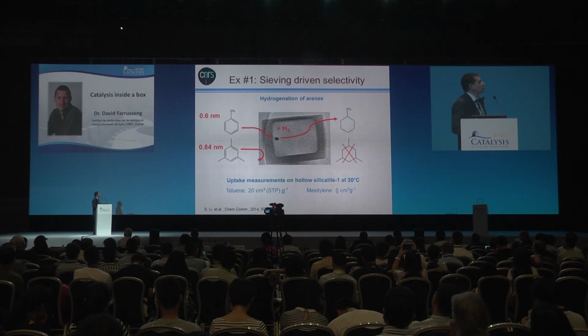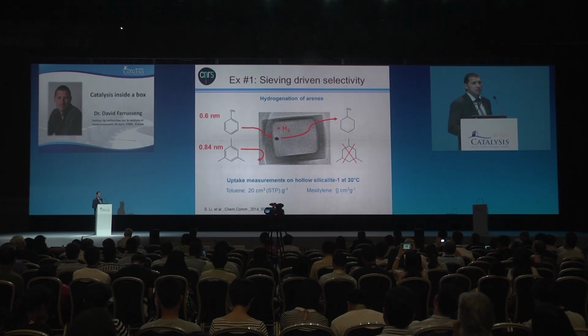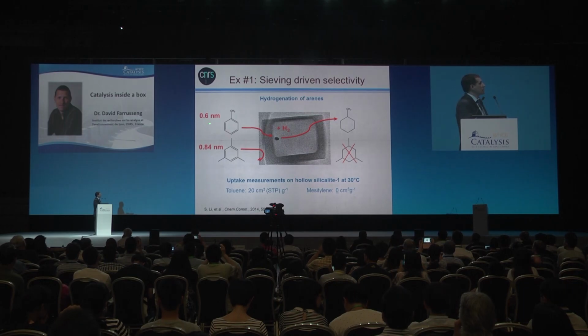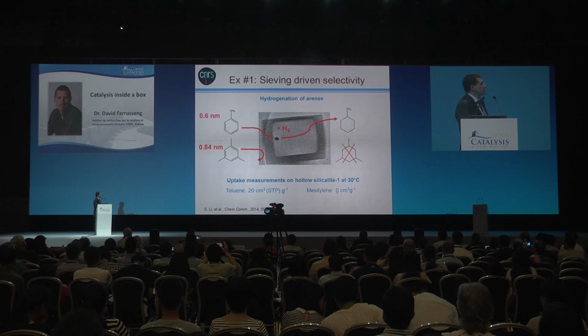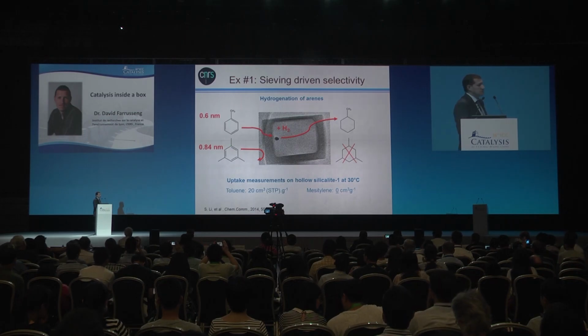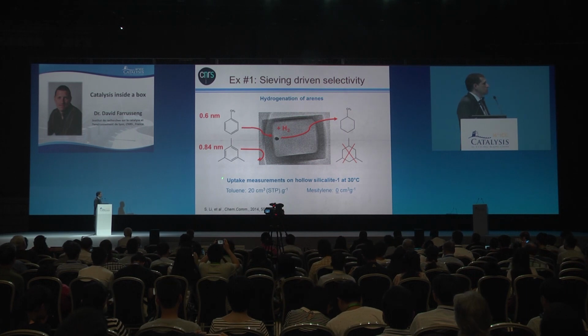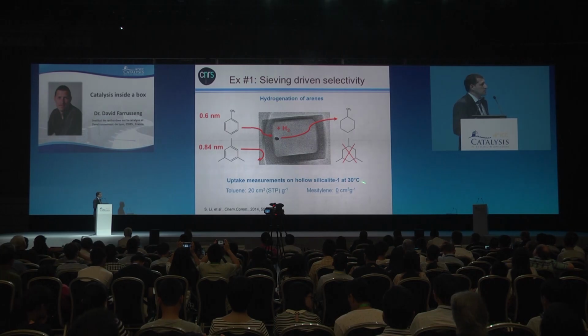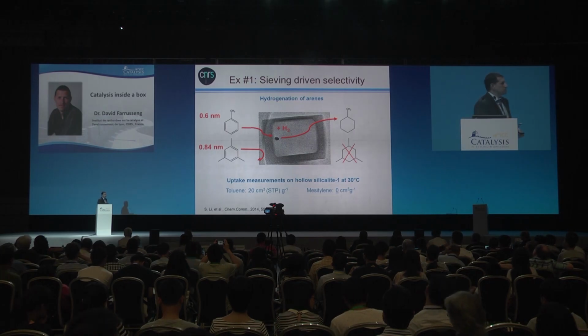So first, how we can use the sieving property of zeolite membranes to enhance the catalytic properties. For example, what we want to do is to hydrogenate toluene and not trimethylbenzene, and so we know that prior to that we did some adsorption measurements, and we can see that toluene is able to enter into the cavity, whereas mesitylene, or trimethylbenzene, is not.